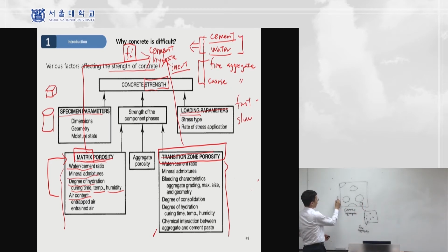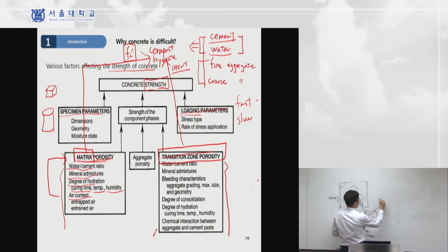So the typical size of the coarse aggregate is 25 millimeter. So you can get a sense of the scale of this material. And fine aggregate is less than a few millimeter, right? Few millimeter to 2 to 3 millimeter. Okay. So this is the scale of the concrete materials. So we call the remaining volume of these a cement paste.